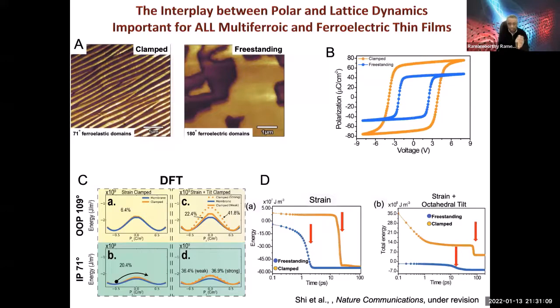I'm really glad. Of course, I went through it a little bit quickly because what I was trying to do is sample a few universes, depending on what people like. The reason it forms this structure, Priya, is because the spontaneous distortion in bismuth ferrite is very large. It's several percent, 7 or 8%. It's a huge distortion, because the polarization is huge, 90 microcoulomb per centimeter squared. So when you put it on a substrate, and this is grown on a dysprosium scandate substrate, you want to think of it as something like a rectangular substrate. It's not like strontium titanate, which has 4-fold symmetry. This has 2-fold symmetry.